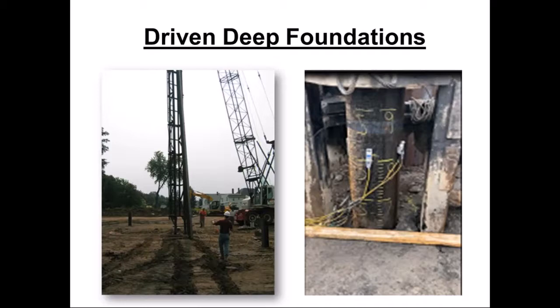So what the inspector needs to do, you can see that this pile has marks on it. So during the testing, the inspector is going to monitor how many blows of that hammer it takes to advance that pile each 1 inch into the ground. And from that information, as well as the testing that's being conducted, they can determine how many blows per inch is required to achieve a capacity for that pile.